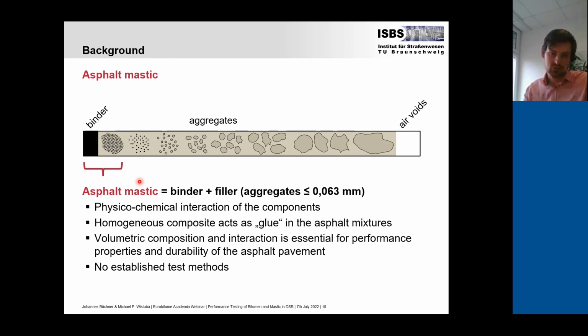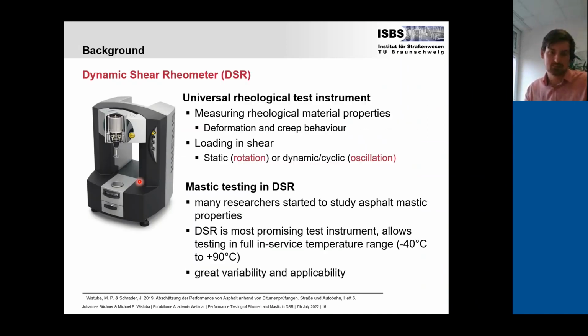So in the Vegas project, which I'm now presenting, we basically looked at simplification of performance testing, as you saw before, by performing the test on mastic and developing new mastic tests. We used the dynamic shear rheometer, which is a universal rheological test instrument to measure rheological material properties, so deformation and creep behavior. It's a very versatile instrument. We can do the loading in shear, either static loading and rotation or dynamic cyclic loading and oscillation.